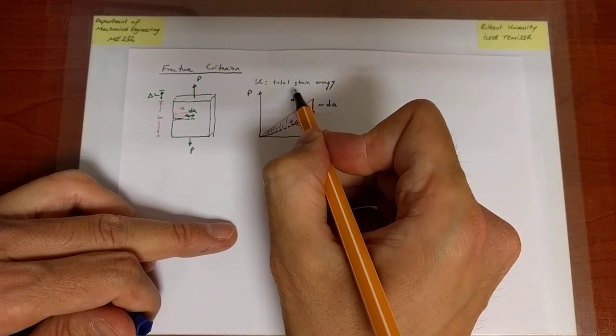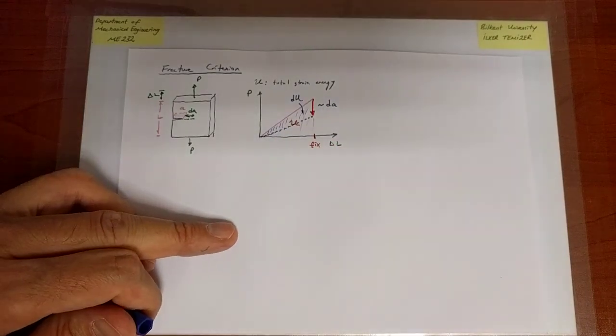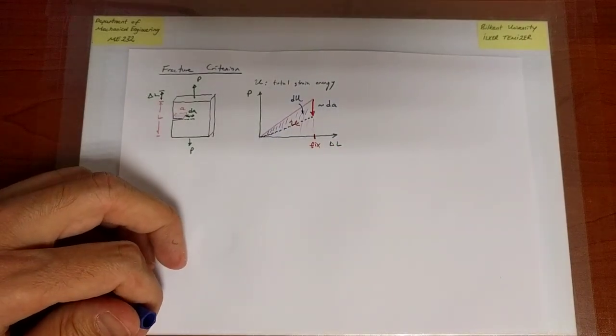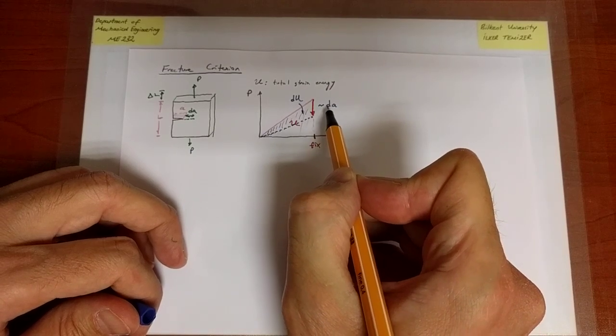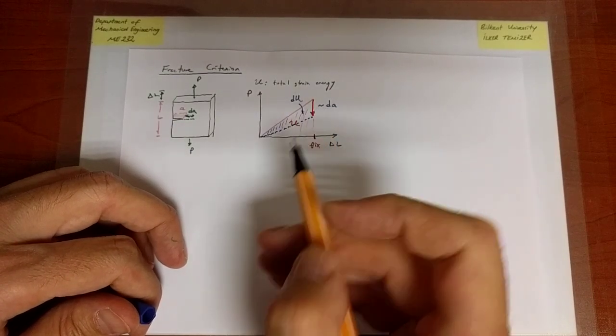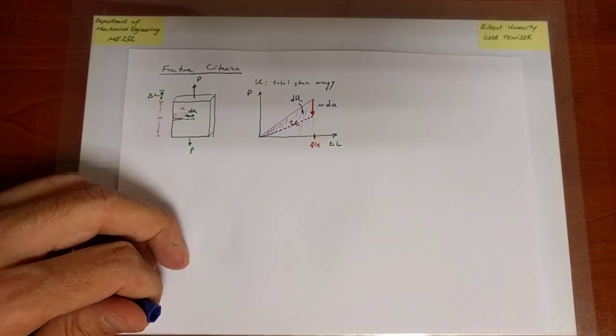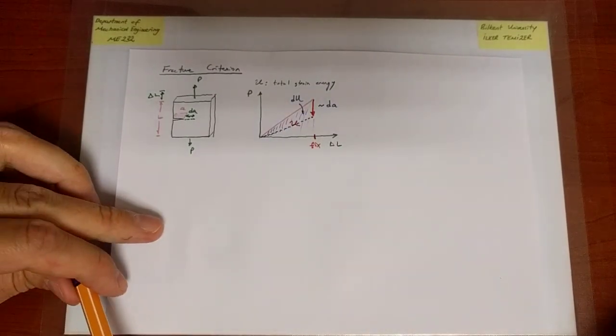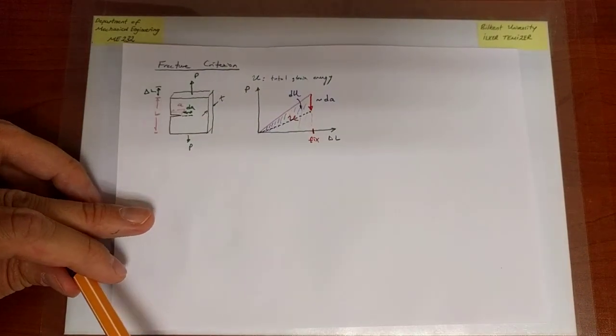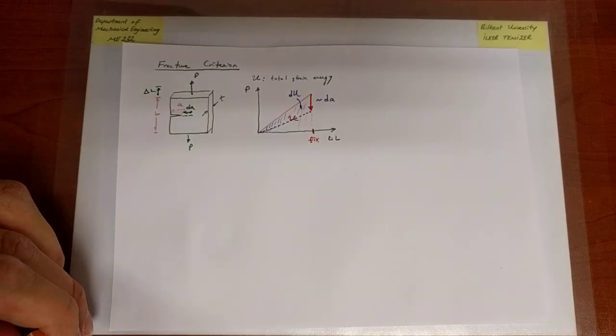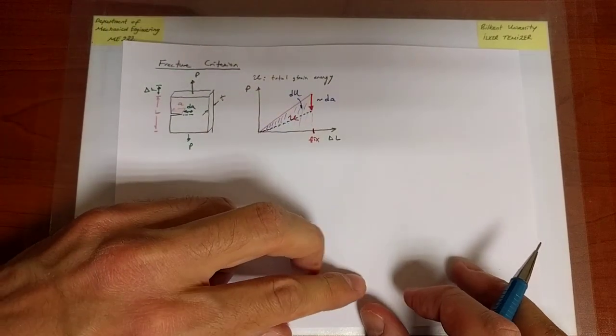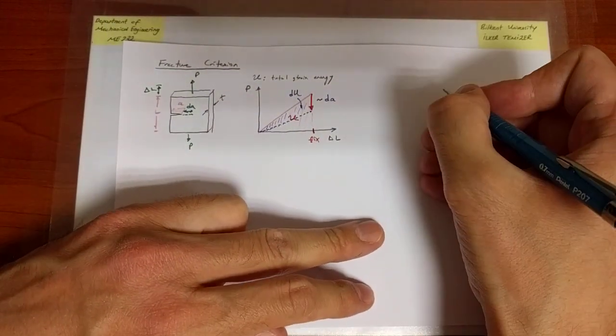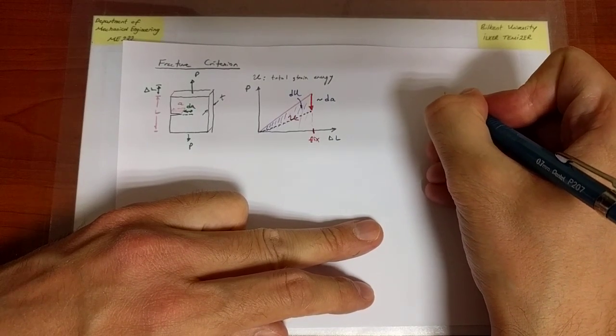Let's call that dU. It's a change in the amount of energy that has been stored due to the fact that the crack has been propagating. I am indicating the crack propagation with an incremental value because I assume it's a very small value, and hence the change in the strain energy is also going to be small. Now let's say the thickness of this plate is T, and what I'd like to calculate is the amount or the rate at which the strain energy is released.